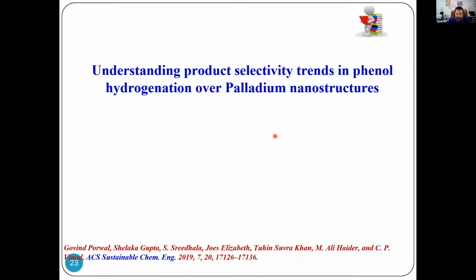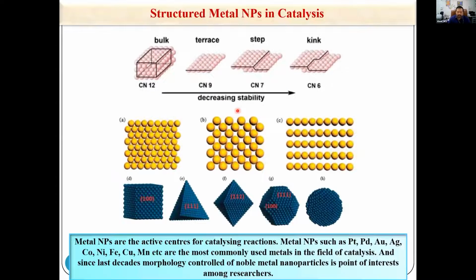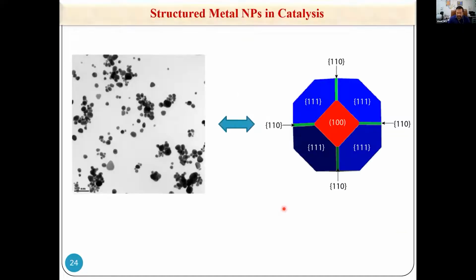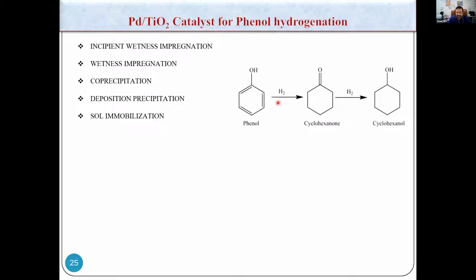In the last few minutes, I'm going to talk about another area which again uses structured palladium nanoparticles, but this time looking at phenol hydrogenation to cyclohexanone and cyclohexanol. Again, we have looked at a palladium cube, which carries 100 surface, an octahedral particle which carries 111 surface, and a normal spherical particle which carries a mixture of 111, 100, and 110 planes. If you look at a normal spherical nanoparticle using a Wulff reconstruction, you will see that the major surface is basically 111 surface. 70% of the nanoparticle carries 111 plane, close to 20% will be 100, and the rest will be 110 planes.